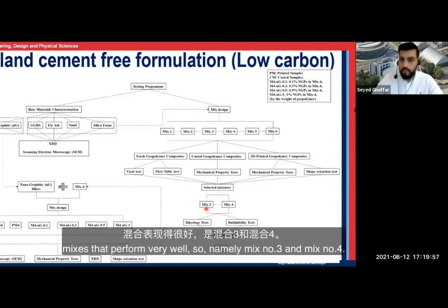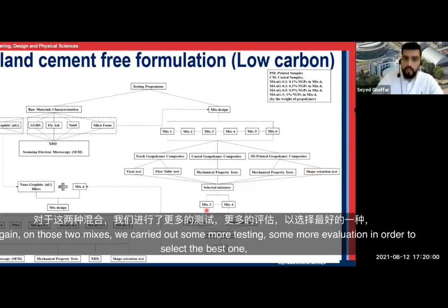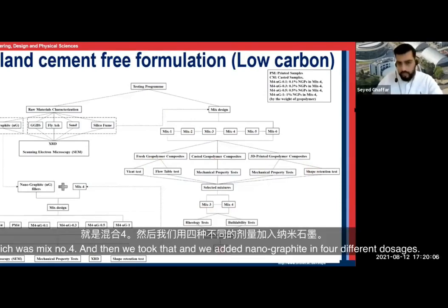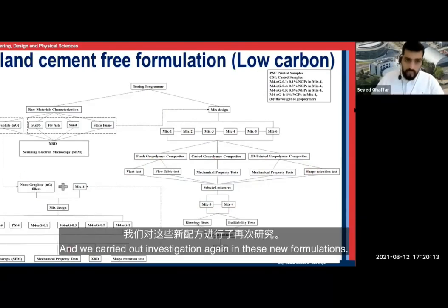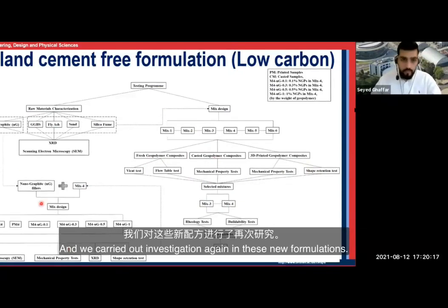So, namely, mix number 3 and mix number 4. Again, on those two mixes, we carried out some more testing, some more rheological evaluation in order to select the best one, which was mix number 4. And then we took that and added nanographite in four different dosages, and carried out investigation again of these new formulations.